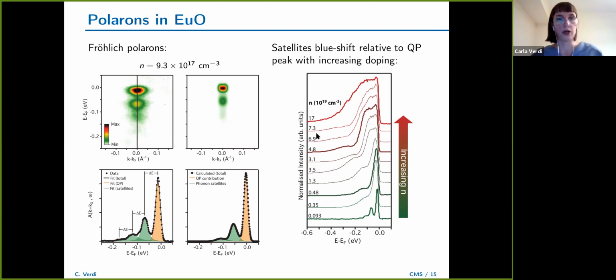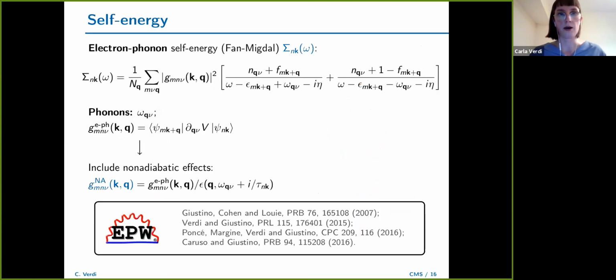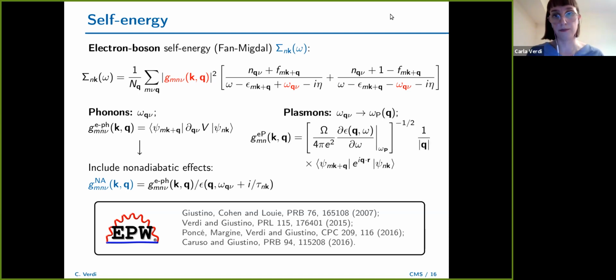Now this is not compatible with interaction with phonons, because the phonon frequencies change very little with the doping, and actually it could only decrease, not increase with doping. So what this hints at is the fact that now our electrons are coupling to the carrier plasmons. So I'm just going quickly back to the slide before where I showed you the self-energy, because I wanted to tell you that this self-energy can be generalized to describe the interaction of electrons with bosons in general. And we showed that in particular, if you take this energy as the plasma energy, then the matrix element has this form here. I'm not going into too much detail, but it's basically analogous to our Fröhlich polaron.